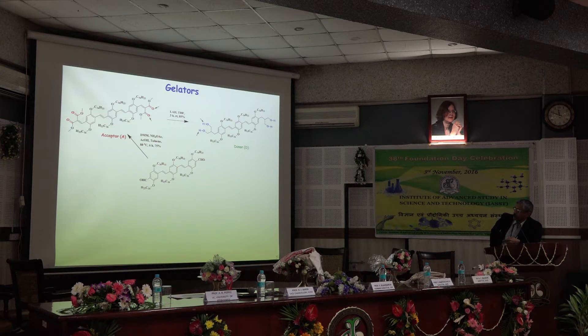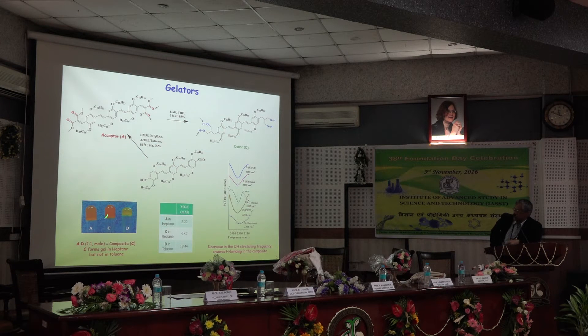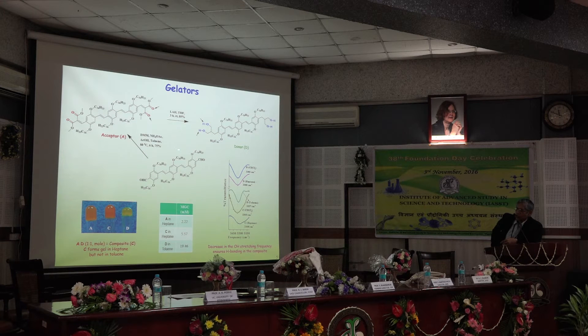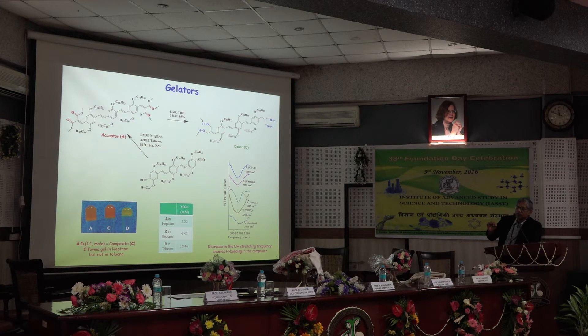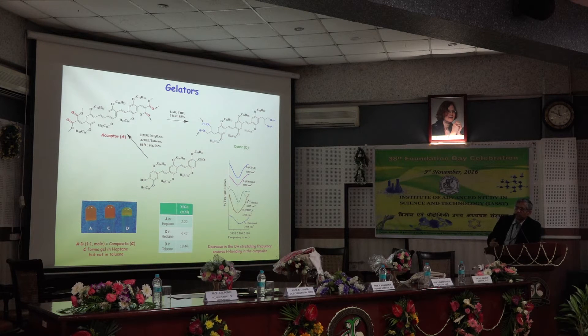If you put them together, you find both acceptor and donor form gel. Their mixture — one-to-one mixture — also gives you gel. So there must be some cross-talk between these two molecules. You can follow this by IR spectroscopy. You can follow also the minimum gelator concentration, which essentially tells you how many molecules would actually immobilize how many thousands or tens of thousands of solvent molecules. One molecule can actually immobilize several hundred thousand molecules — that's why the gels are formed.